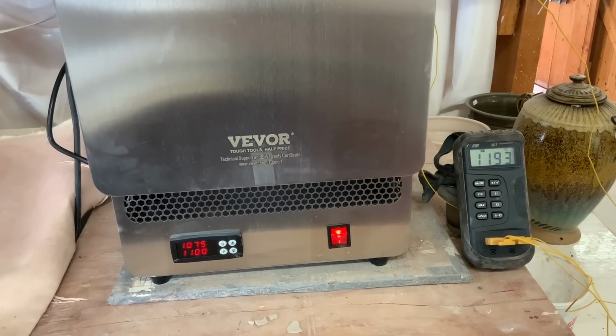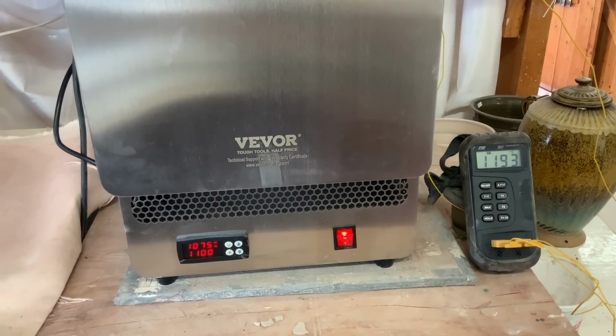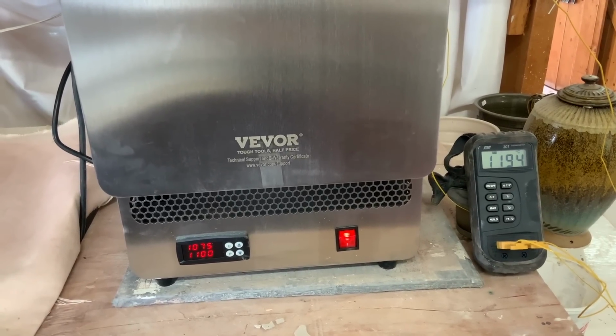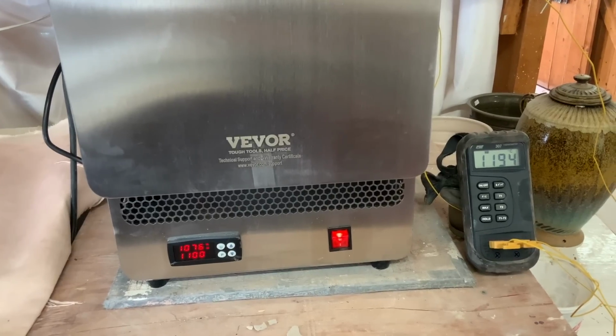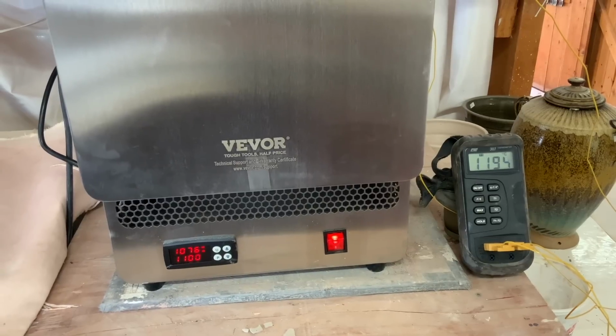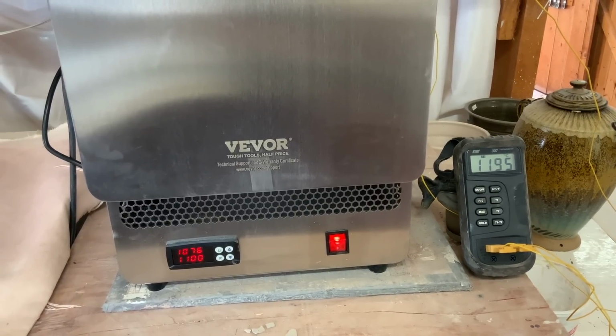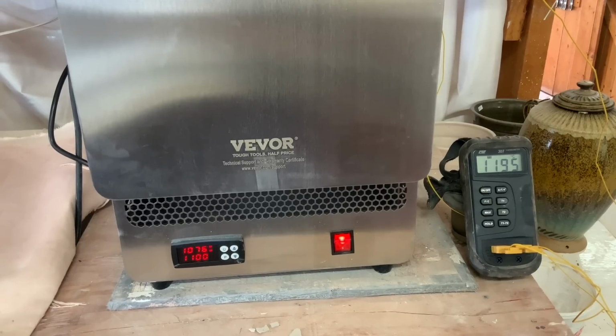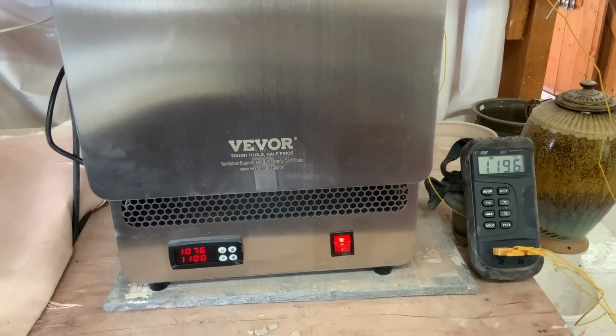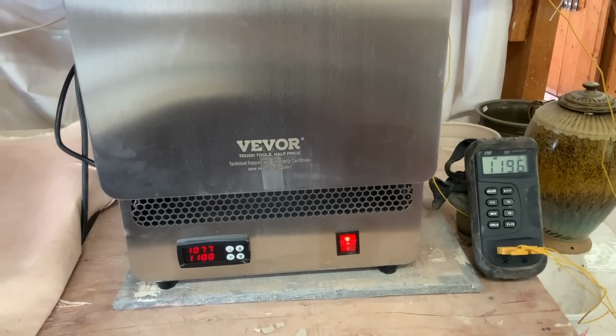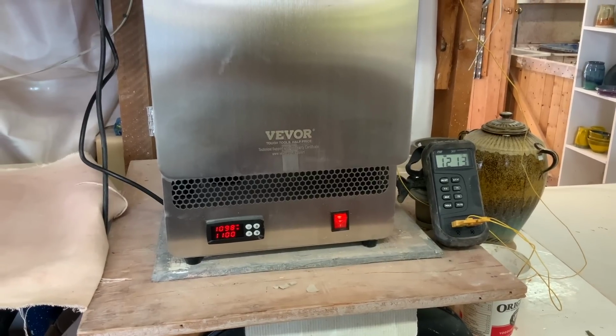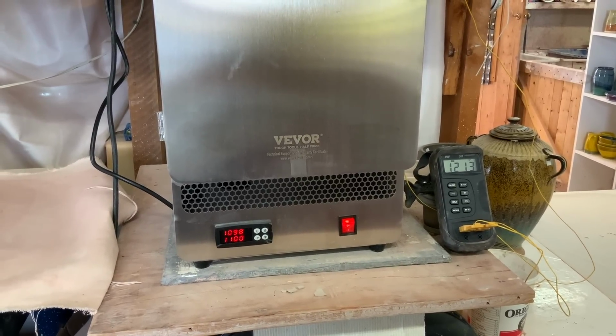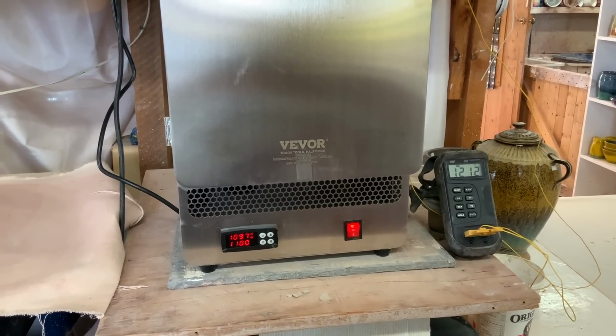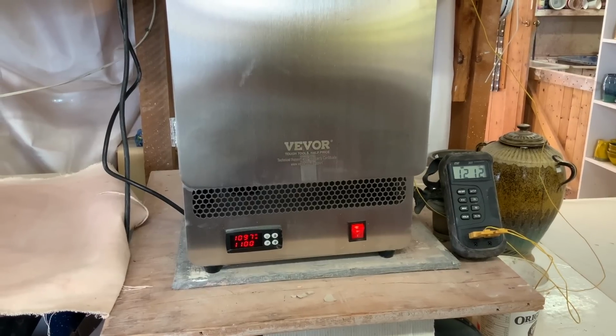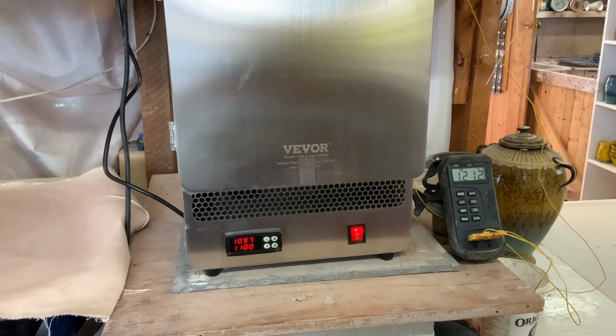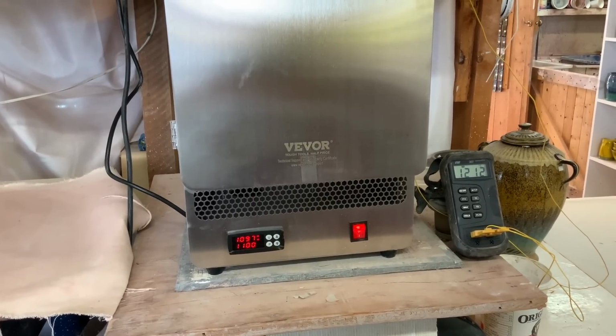I just reprogrammed it by pressing the U button and raising it to the 1100 on the kiln, and my thermometer is reading 1194, so I'm going to try and take it up to 1100 and hope that my temperature on my kiln pyrometer will go up to about 1220, and 1225 is optimal, I think. Okay, things have been rising a little slower because it's quite high temperature now, but we're reading close to 1100, 1097 and 1212 on my pyrometer.